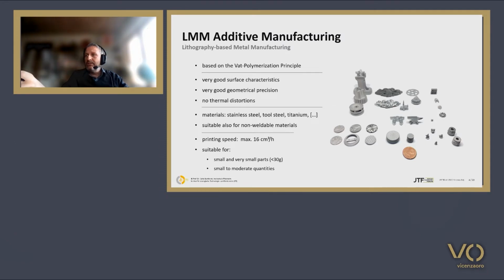Currently, we work with stainless steel, with tool steels and titanium, but as I said, we are currently starting also with precious metals. The whole procedure is also suitable for non-weldable material, which is important if you want to do material mixtures. The printing speed is about 16 cubic centimeters per hour. That's not very much for industrial purposes for large scale, but it's very interesting for small scale and also, we think, for jewelry production.